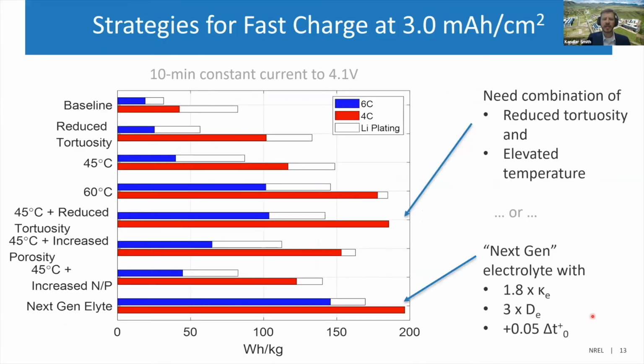So with this knowledge, Andrew has taken the model and scaled up to higher energy densities, 3 milliamp hours per centimeter squared. I think now we're in excess of like 200 watt hours per kilogram. The baseline cell could only charge at a 6C rate if it hits the 4.1 cutoff, just to like 30 watt hours per kilogram. So that's pretty shoddy. If you do things like reduce the tortuosity to improve the effective electrolyte transport rate, you can do better. If you go to modestly elevated temperature, 45 Celsius, or very elevated temperature, you do a lot better. So the electrolyte transport gets a lot faster at these elevated temperatures.